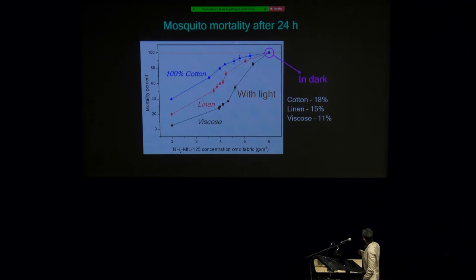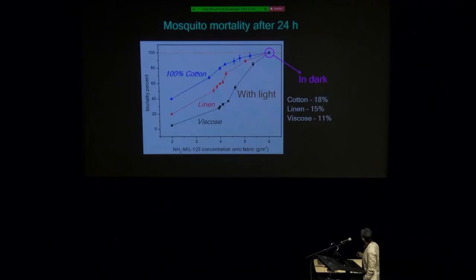So then we studied mosquito mortality after 24 hours, trying different concentrations on fabric from about 2 to 6 grams of metal organic framework per square meter. And we also tried different fabrics. And you can see that with 6 grams per square meter, almost all mosquitoes are dead in the presence of light. In the dark, it's a different matter. We have much less mortality.